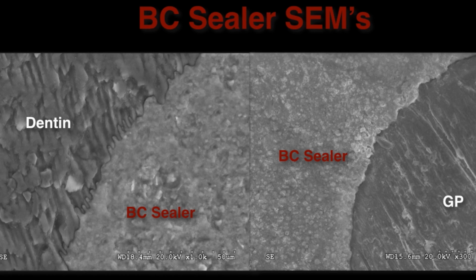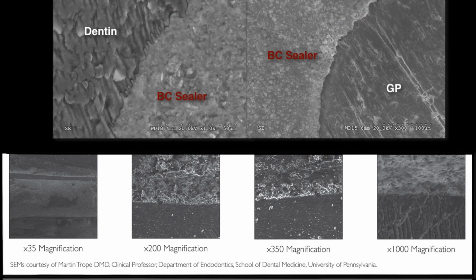So studies have also shown that you do get a nice chemical bond between the silanated surface of the specific gutta-percha cones, which is the EndoSequence and ESX gutta-percha cones, with the bioceramic because of the silanation. And then also you get a chemical bond to the dental wall. So in a sense, you do get this kind of a monoblock. However, the beauty of it is that this technique is retreatable because the main gutta-percha cone in the middle is soluble in chloroform, and then you remove that, and then you have just the rest of the ring of sealer around the cone that you would then remove by going one or two sizes up in your files, and you can use at the end some ultrasonics in order to shatter any remaining cement and remove it.